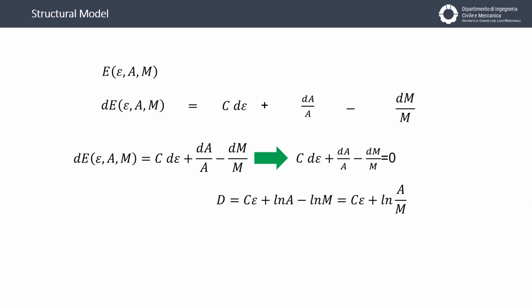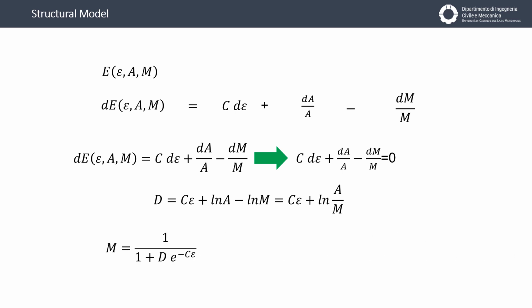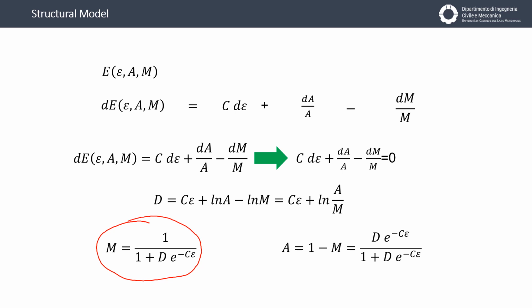And integrating this equation, you can see that the formulation is very, very easy. A constant d is equal to the constant c, which multiplies the deformation, plus the logarithm of austenite on the martensite. Taking into account that the summation of the quantity of austenite and martensite is equal to 1, you can calculate the quantity of martensite like this, and the quantity of austenite like this.